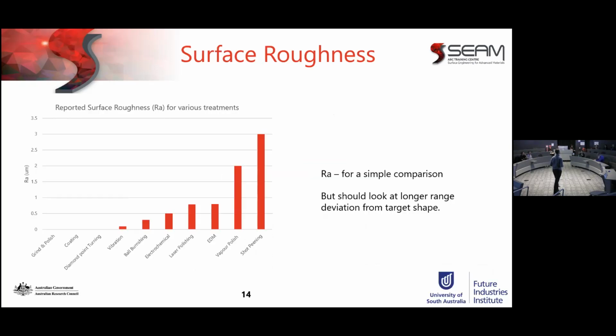Okay. A brief comparison of the typical surface roughness that you're going to be expecting. So the very best, you're in that grinding, polishing, coating, I'll get to in a second as part of the case study. Diamond point turning, it's in the nanometers of roughness. So the scale there's microns, those ones are in the nanometer of roughness. Then you start getting worse and worse as you go.